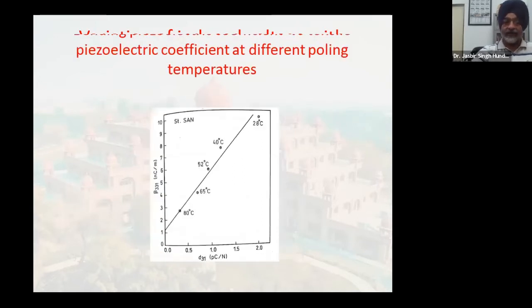Okay, and this is correlation between D31 and beta 331. Okay, where the poling temperature had been kept different, right? So this is what we get. They all points. They almost have a linear relationship between the two, right? If D31 is affected, beta 331 is affected too. That is the simple thing we have. Now this is in case of ABS. Okay, with the poling field, we have the variation of D31.